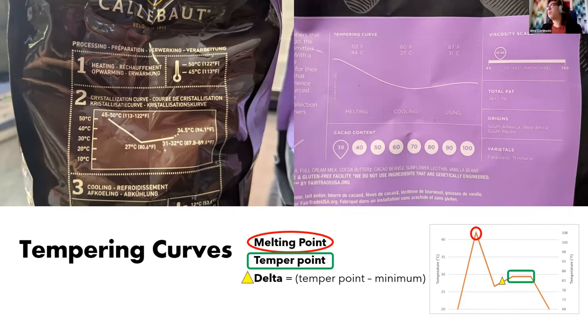Oh, and the relative humidity question. When you're tempering chocolate, you want less than 50% relative humidity in the room you're working in. That can be hard to achieve, I understand, in more humid climates. But a way to do that, I've found, is to create a low humidity chamber by maybe taking a box and putting some dehumidifying powder in there. Just whatever you can do to lower the humidity below 50% when you're working chocolate.